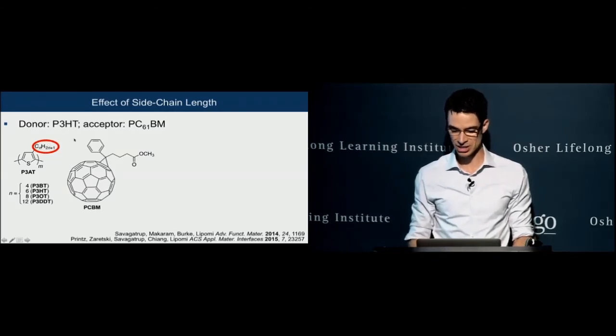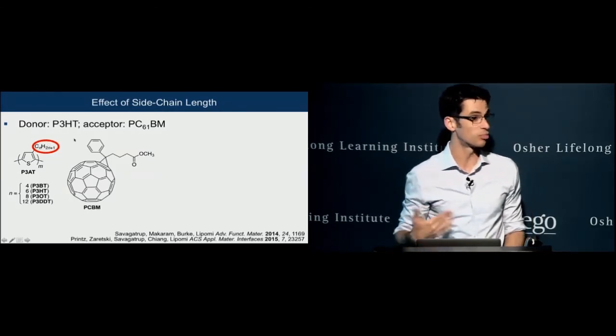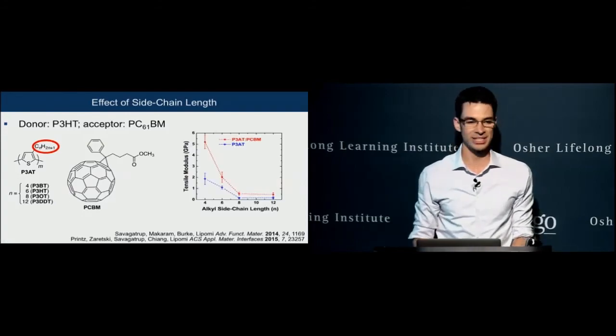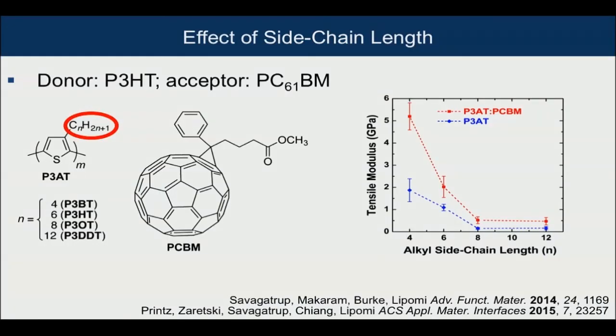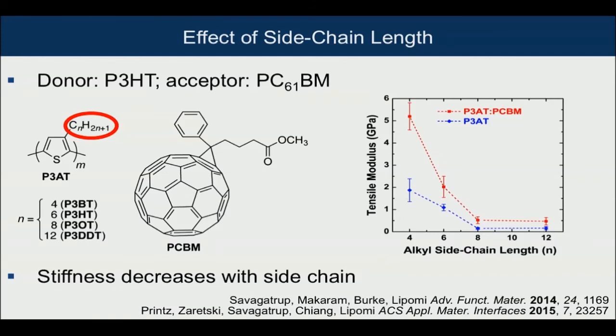Now with the side chain, you get changes in the properties. The longer the side chain is, the less stiff it becomes. So this is a plot of the tensile modulus, which is like the stiffness, versus the length of the side chain. So the stiffness goes down as the length of this side chain goes up. So those are some of the characteristics that we exploit in order to make our materials more like skin.